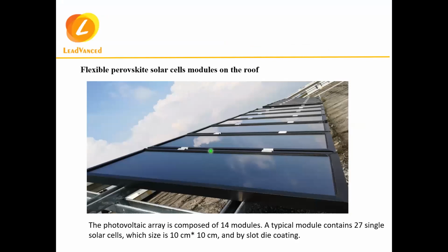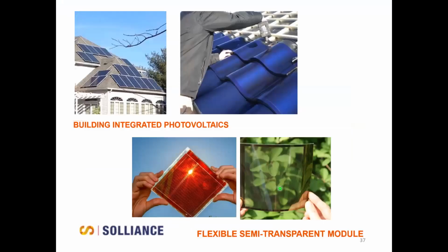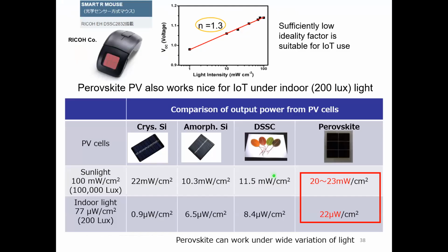And okay, this is a rooftop application, and the window application is almost attractive. The solar cell can utilize light from both sides of the device. Another application is IoT. In Japan, a company commercialized this one for use with computers. This was attached to a solid-state dye-sensitized solar cell. But if we replace this with a higher efficiency perovskite solar cell, the power output under indoor light, like 200 lux, very weak light, can reach 22 microwatt. This is much, much higher than the power produced by silicon under indoor illumination, because silicon cannot utilize infrared.